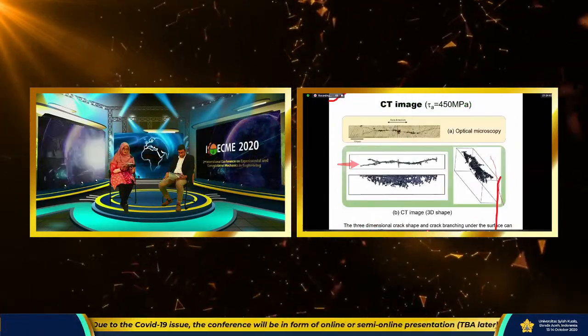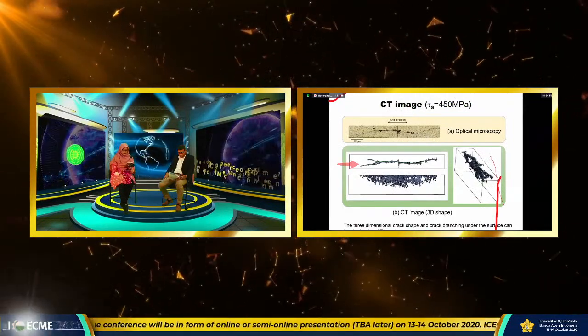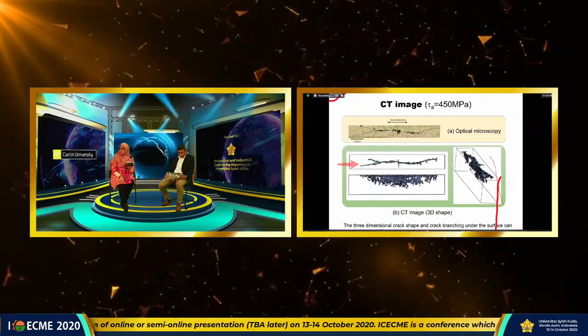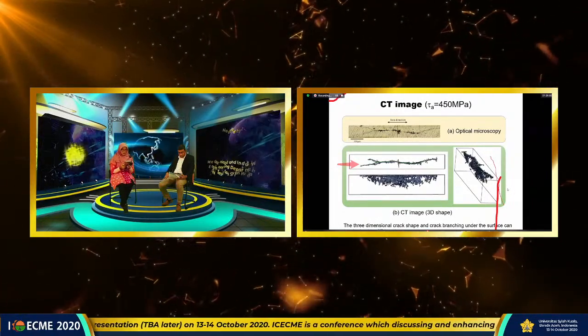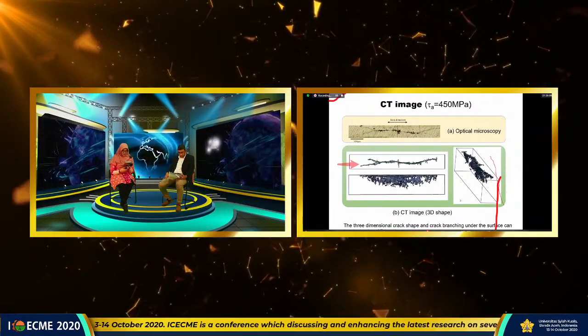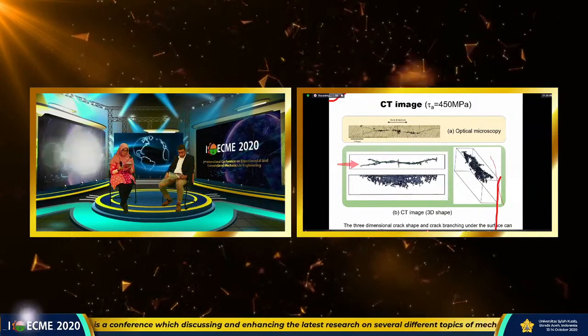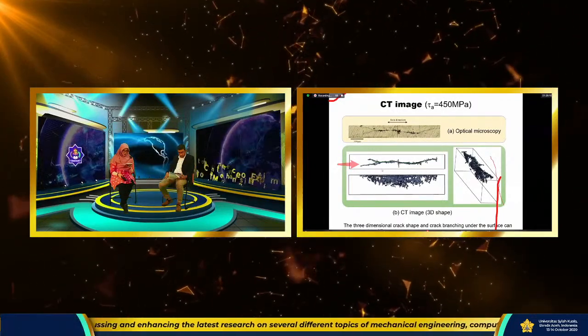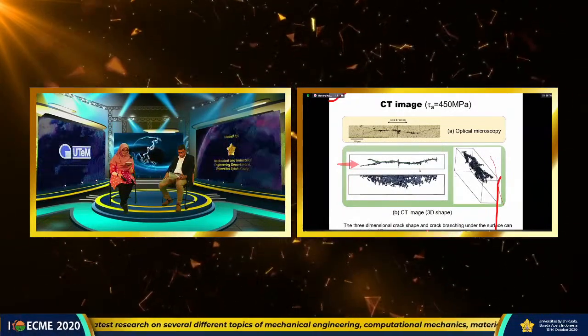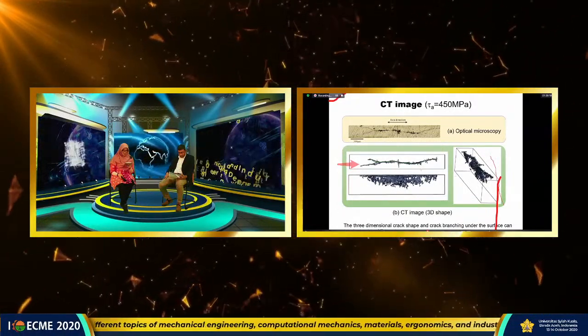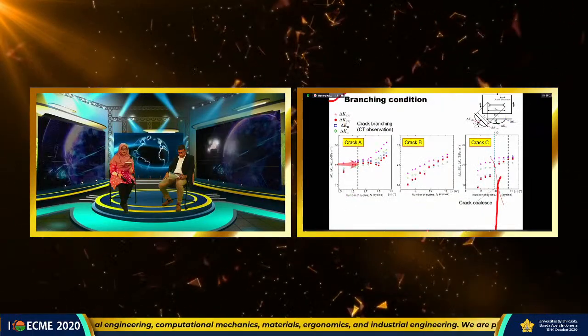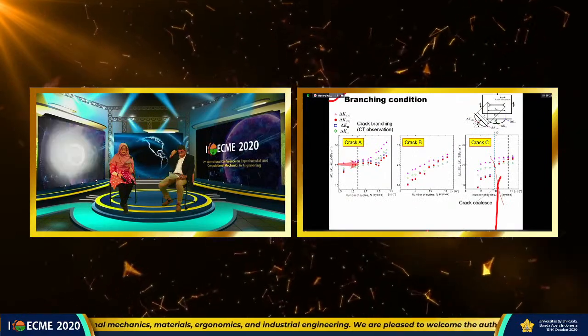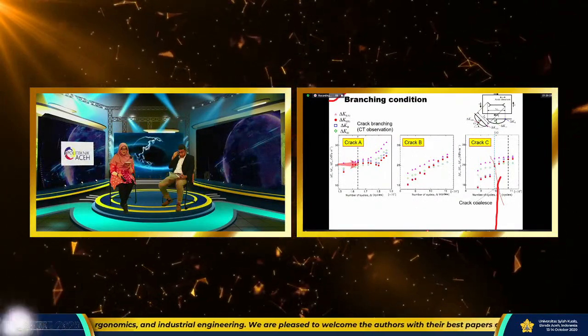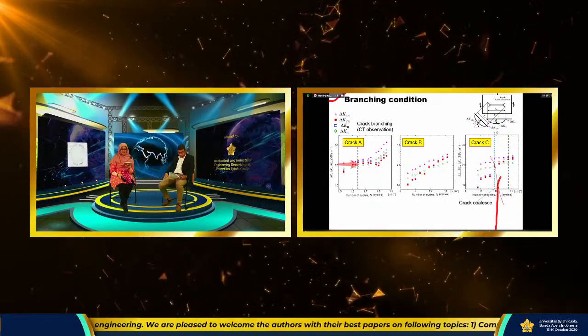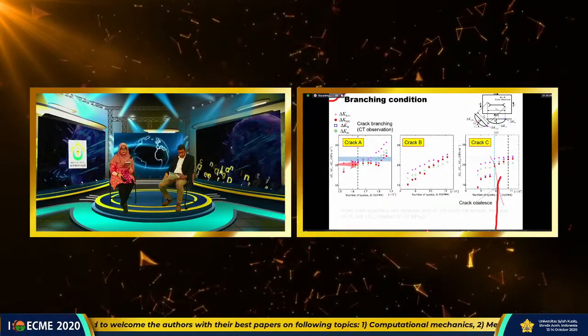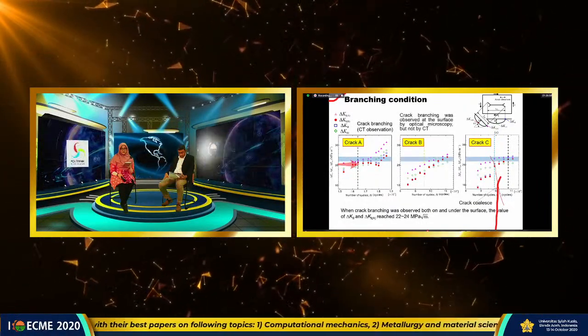So we applied refraction contrast imaging to observe torsion fatigue cracks. This is the result, an optical micrograph observed from the surface. You can see the branching like this. This figure shows the CT imaging by using the synchrotron facility. You can see also branching like this, and like this. This shows the change of stress intensity factor during the fatigue process for several cracks. I don't want to go into detail, but I just mention the branching condition can be determined by the stress intensity factor like this.